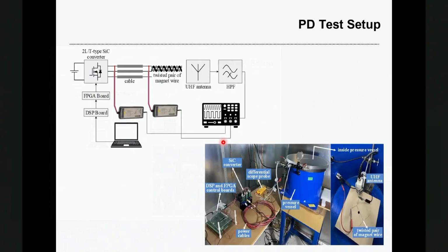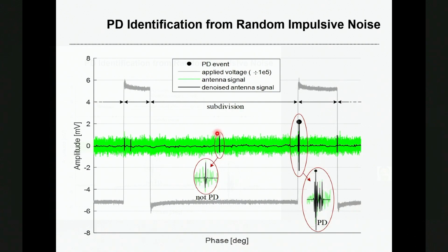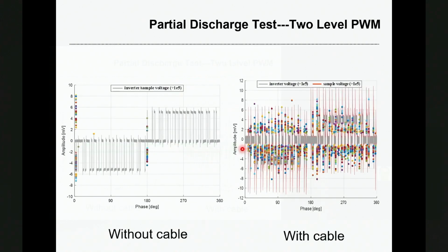And we have measured the partial discharge events in experiment with a silicon carbide converter driving twisted pair. And we have detected the PD events and put that in the phase diagram with the voltage waveforms. For example, this is with a two-level converter without any cable connected between the inverter and the twisted pair. You can see there are only PD events, partial discharge events, when the polarity of the pulses changes from negative to positive or from positive to negative.